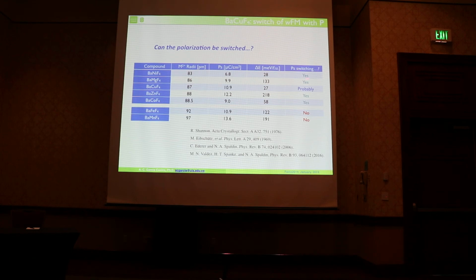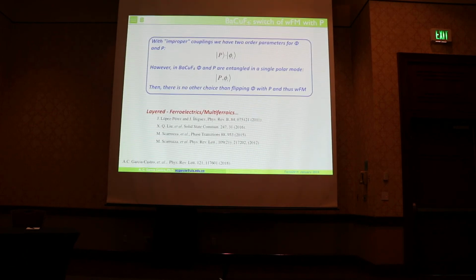However, when we look at the switching, these two members have been experimentally reported to be real ferroelectrics, and these two, they haven't been switched. And the copper, when we analyze where it is in the table of the family, probably it can be switched, but that's something that we hope some experimentalists will test. Again, to remark, in the improper couplings, what we have is this type of expression where the polarization is coupled with the rotations. However, in BaCuF4 or in the whole family of materials, the rotation and the polarization are entangled in a single mode, which is the perfect one for this type of application.